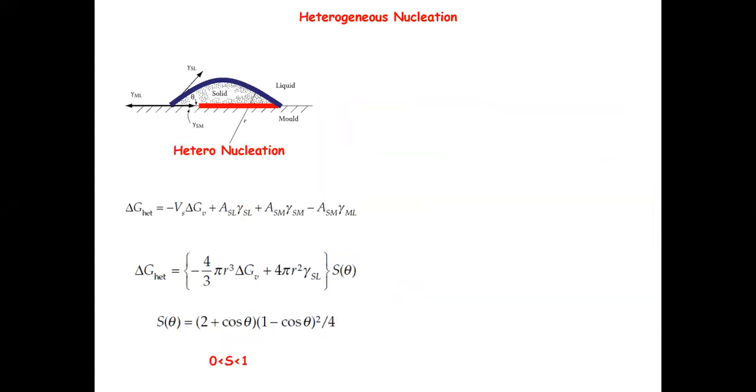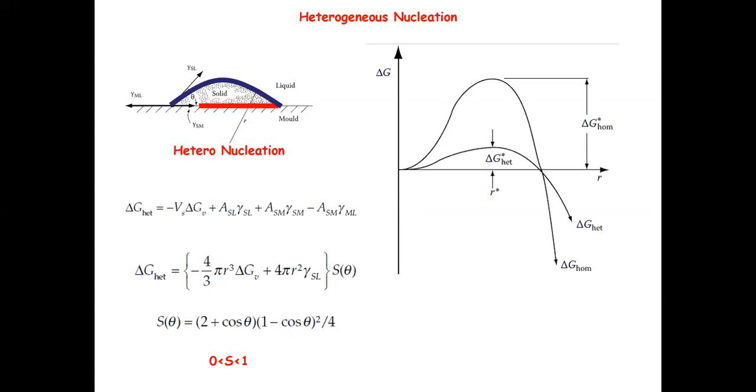Exactly, because the energy cost for this, you know, I just write down everything here, but if you look at the original plot that we had for nucleation, this is going to be my homogeneous nucleation curve. Does that make sense? Right, so I have a huge energy barrier, but then what is the relation between the homogeneous and the heterogeneous nucleation? I multiply the homogeneous nucleation equation, this whole curve, by a factor which is typically much smaller than 1. For normal theta, it's typically very small, right? So this whole function is very small compared to 1.